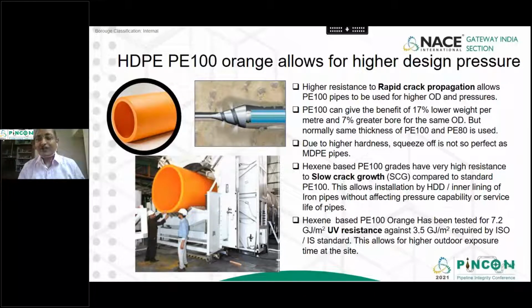Depending on this consideration, MDPE and HDPE materials are used for a lower pressure in gas. Now, while MDPE material typically has a rapid crack propagation resistance of 4 to 5 bar, PE100 material has a rapid crack propagation resistance of up to 10 bar. That's why for higher pressure, typically PE100 materials are used.